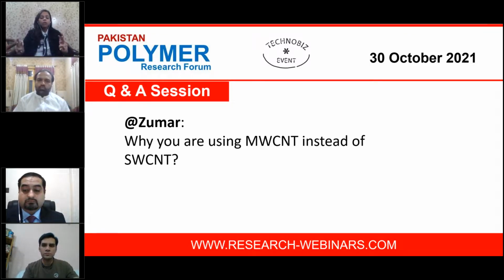And when you yield on industrial scale, SWCNT provides only a 72 to 80% yield. But when it comes to MWCNT, it can give you a yield up to 98%. And purity in SWCNT is achieved with huge difficulty, whereas MWCNT are processed with high purity. Moreover, they are cost effective. That's why we use MWCNT instead of SWCNT.